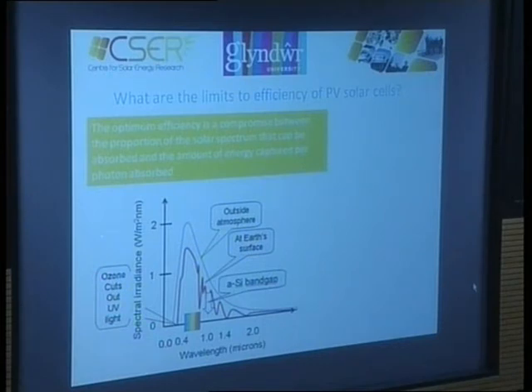So if we look at silicon, for example, it's got a band gap of about 1.1 electron volts, and that will absorb in the near infrared, but further out in the infrared it'll just go straight through. Remember, the photon energy isn't enough to excite these electrons into the conduction band, so it just goes straight through. Okay, so that bit we lose.